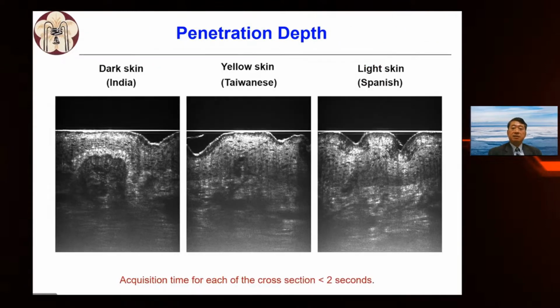The penetration depth apparently also depends on your skin type. In my laboratory, I have an Indian student, a Taiwanese student, and a Spanish student. If you have darker skin, the penetration depth becomes shallower, on the left-hand side. In the middle, for yellow skin, the penetration depth is usually about 300 to 350 micrometer. But for light skin, you can penetrate deeper. The penetration depth depends on many issues, for example the amount of melanin beneath your skin, and also the scattering, because human tissue is highly scattering. So depending on the scattering and the melanin, the overall penetration depth is limited.